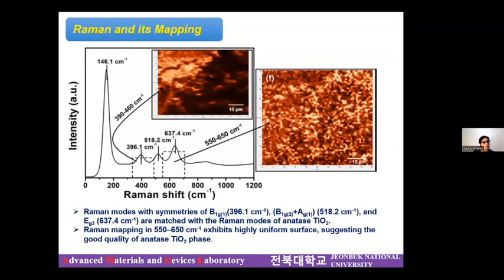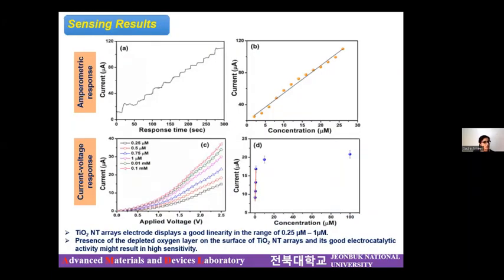Then we performed Raman spectra just to make sure of the structural characterization of the synthesized TiO2 nanotubes. And these are some of the interesting results that we got from the sensing. Since it is an electrochemical method, we performed current-voltage characteristics. We made up different concentrations of phenylhydrazine, a toxic chemical, in the solution, and we found that as the concentration increases, the current response also increases.